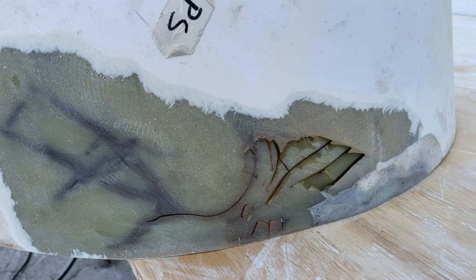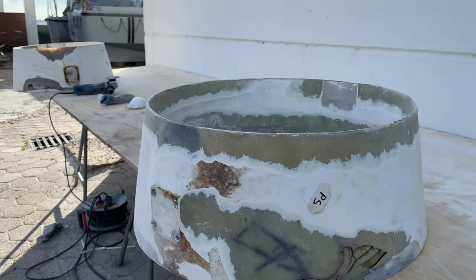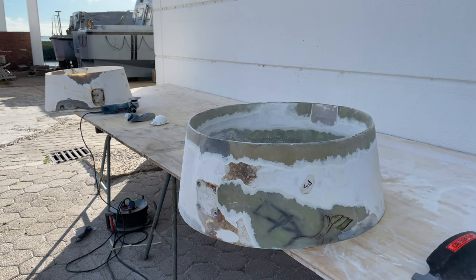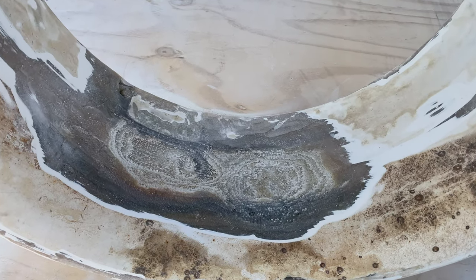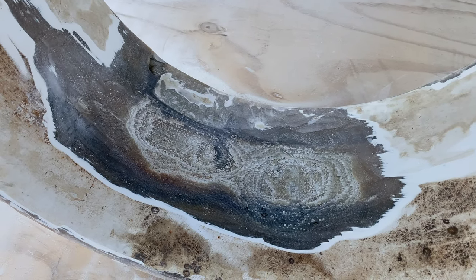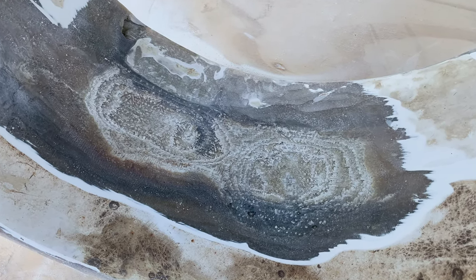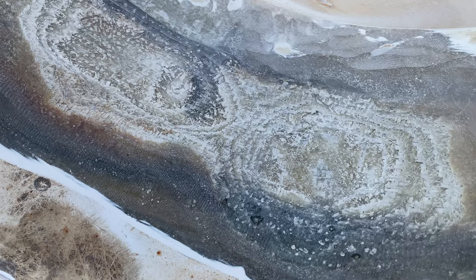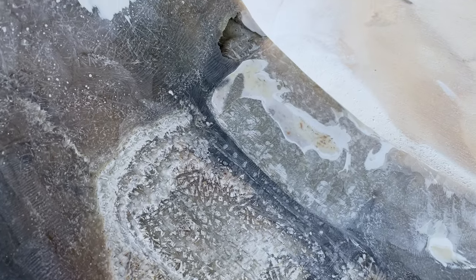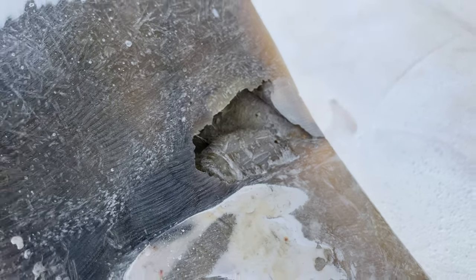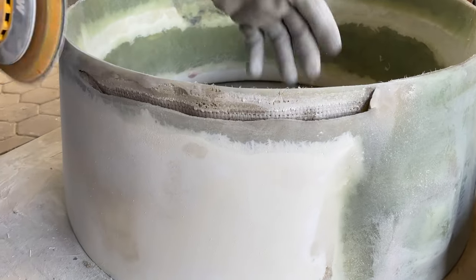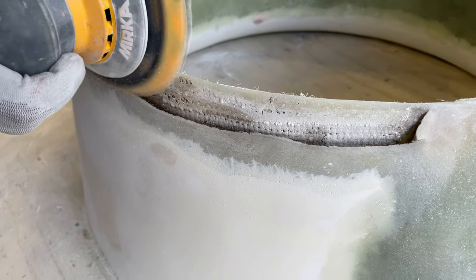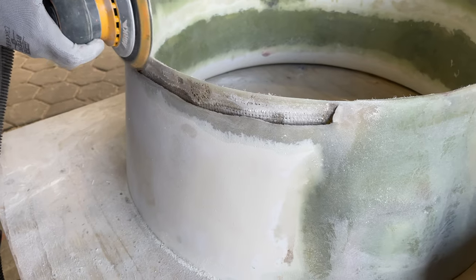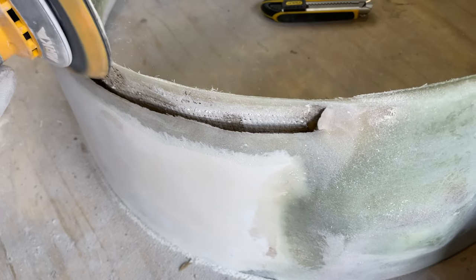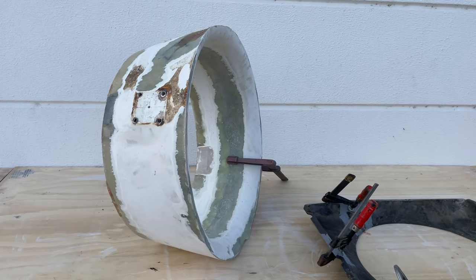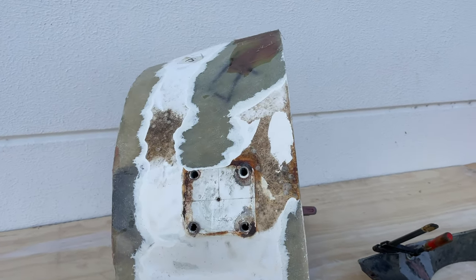And that's where most of the YouTube tutorials that work in a clean white room with a simulated fiberglass damage will leave you. It's just not possible to do it the clean and textbook way, because for example here you have this white fiberglass with not much resin in it. If you keep grinding down until you get to the bottom of it, there you have it, you have a hole, and you can't keep grinding down more. So you have to compromise on removing as much material as possible without completely getting rid of the contours, and then the next step is to add some resin.